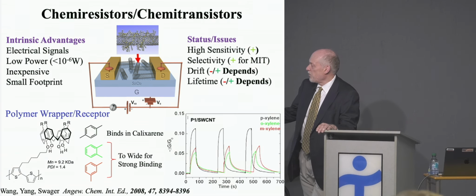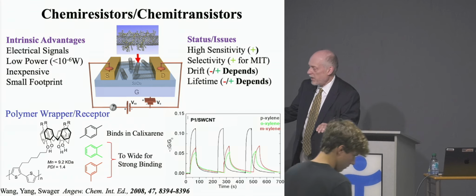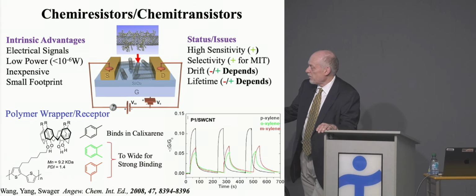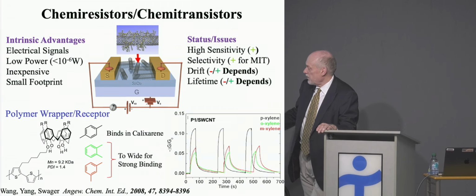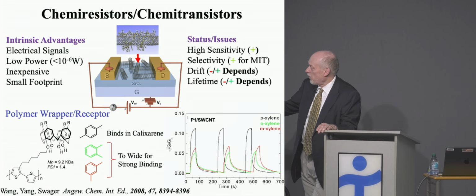And so what we did is we showed that we could determine these. They all have about the same boiling point. They're very similar compounds. They just differ by a little bit of their topology and their structure. But we showed we could get different, essentially, resistance changes with them. So what I'm showing here is essentially the amount of current flowing through this. It's been kind of standardized, it's normalized. But the amount of current flowing through here, when you give it a little blast of one of these vapors and then you turn it off, then it goes back down.